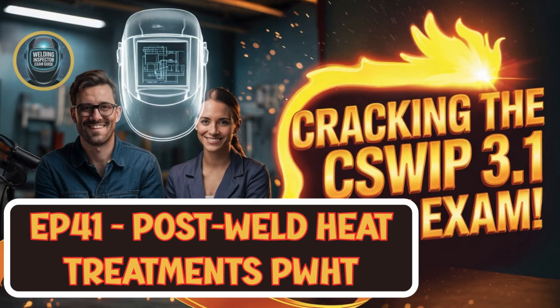It also significantly improves resistance to something called stress corrosion cracking, or SCC. That's a major problem in tough environments. Pipelines carrying corrosive stuff, for example. SCC loves stress, so reducing stress helps fight it. Okay, so better resistance to breaking and corrosion. Anything else? Yes, something very practical too. By relieving those internal stresses, you allow the welded parts to be machined to much tighter, more accurate dimensions. If you've got internal stresses pulling and pushing, the part might distort when you try to machine it precisely. PWHT stabilizes it, essential for parts that need perfect fits.